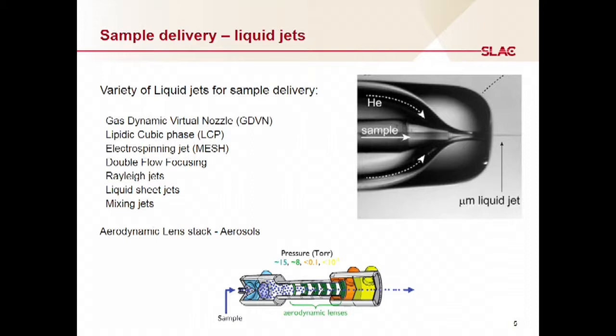It is much better in terms of sample consumption. So if you have a very, very precious sample that you don't want to be gone within half an hour, you should think about using a mesh jet. There's the double flow focusing jet, which is also a very low flow kind of jet technology that has two concentric liquid jets, one inner, one outer. And then what the outer flow does is that it kind of squeezes the inner jet to become even smaller.